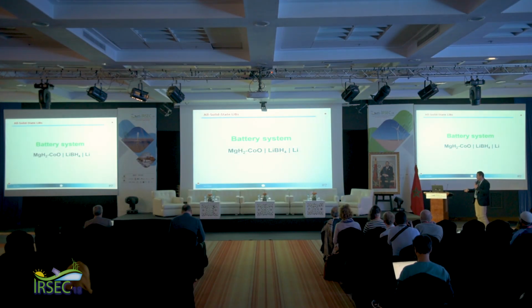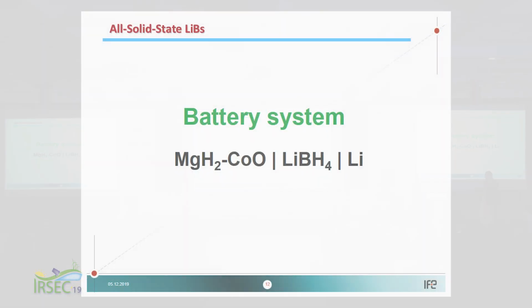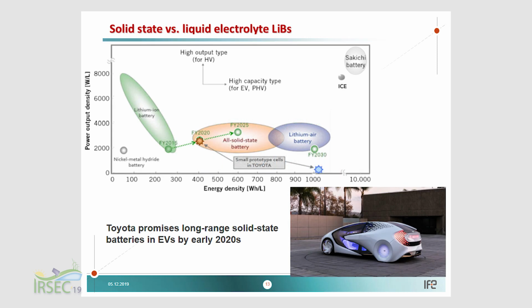So then we moved categorically to the solid state systems, and we used in this case lithium borohydride as electrolyte, and we tried to work with magnesium hydride, also with the addition of some cobalt oxide, which in fact is also a conversion type material.